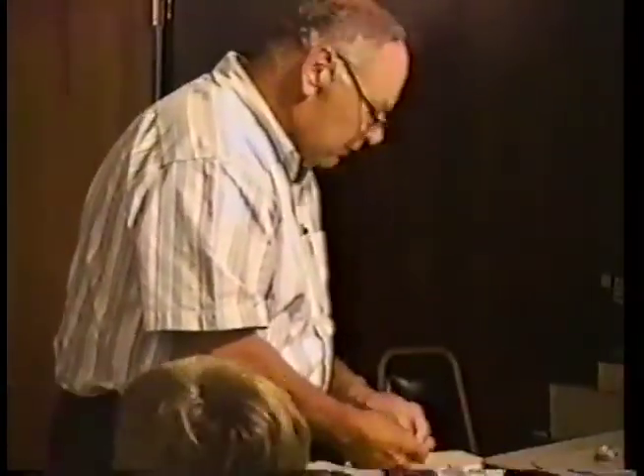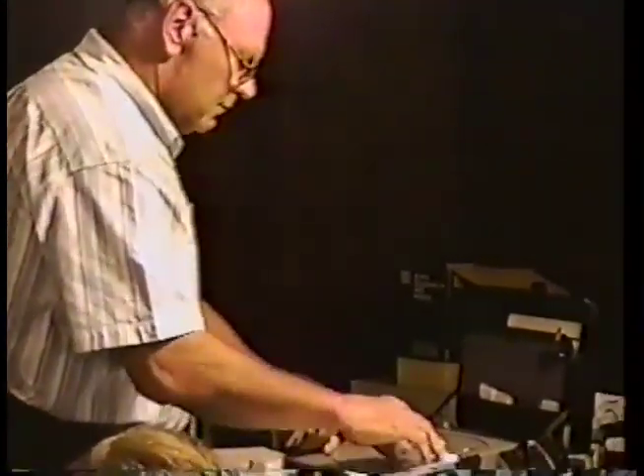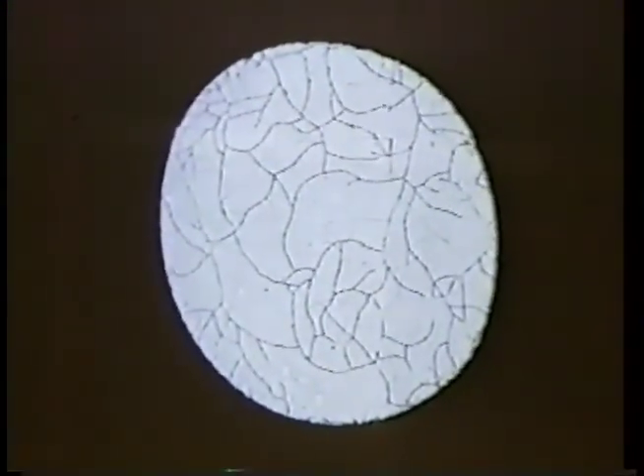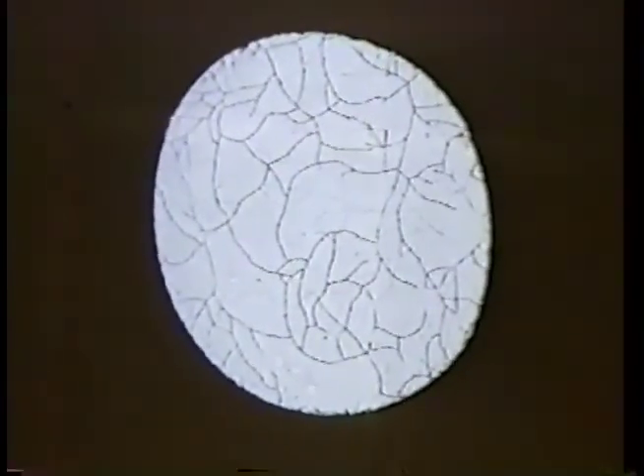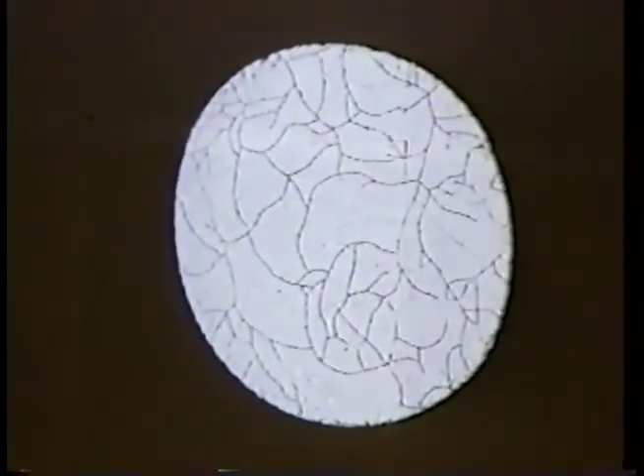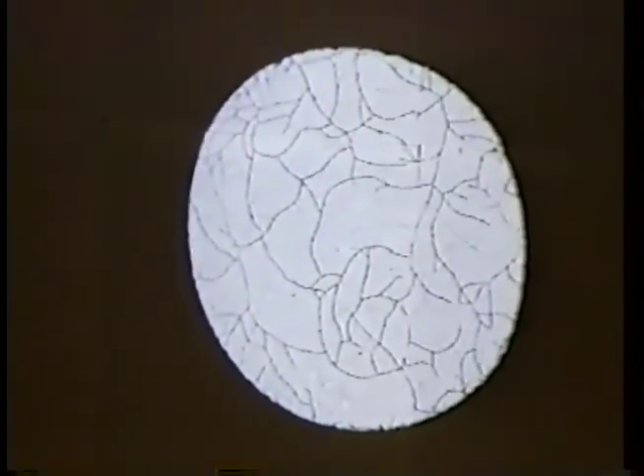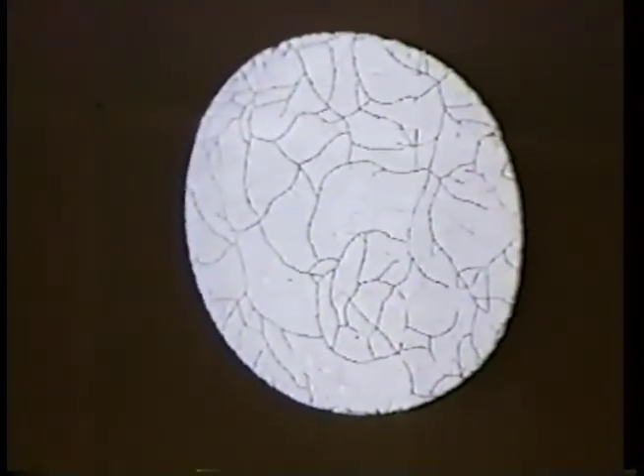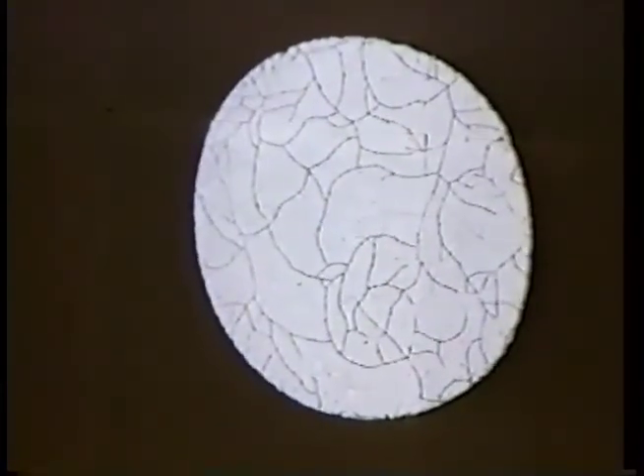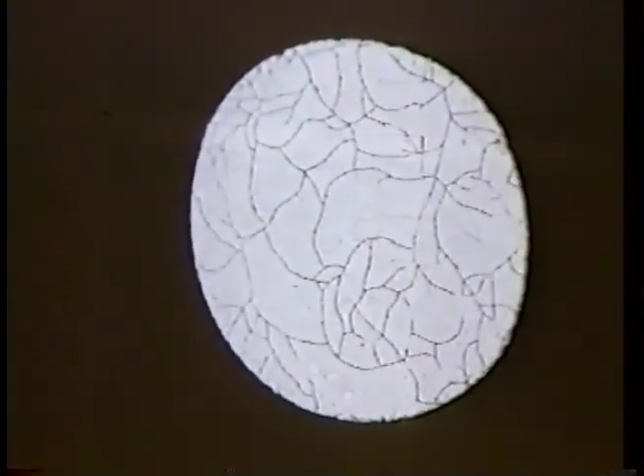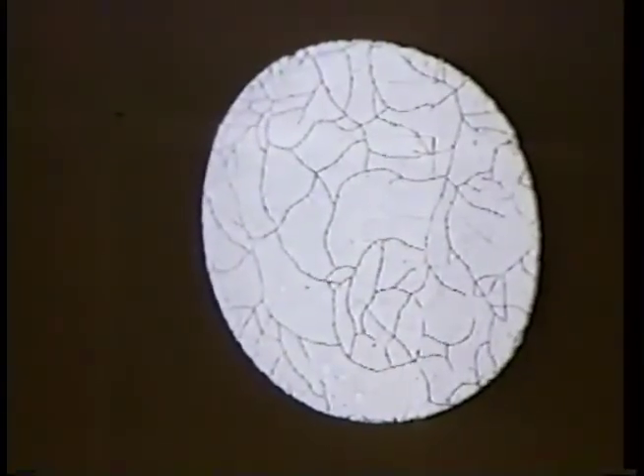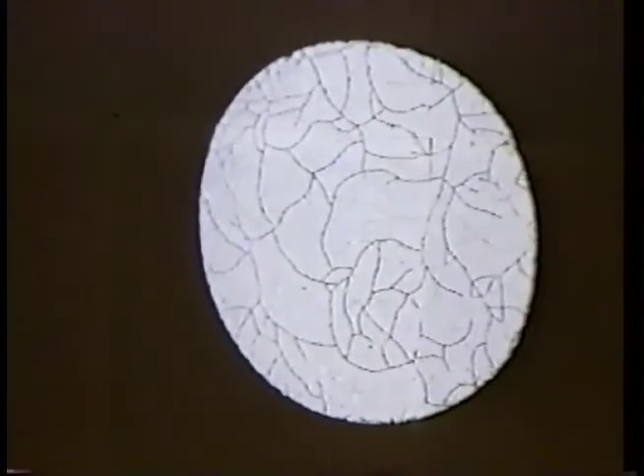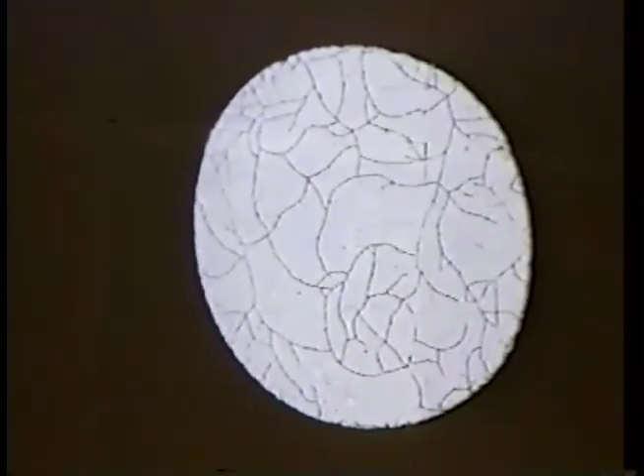What I'd like to show you now is what we had talked about. This is an example of reverse current edge porosity after a period of 24,000 to 30,000 hours in a marine application. I was in our Cleveland plant one day, and these liners came in, Fairbanks liners, from our customer. And in those liners, they had both reverse current edge porosity and our mechanically induced porosity. Both running the same period of time, in the same engine. So it was a good chance to get a good sample of what the finish looks like after a period of service.